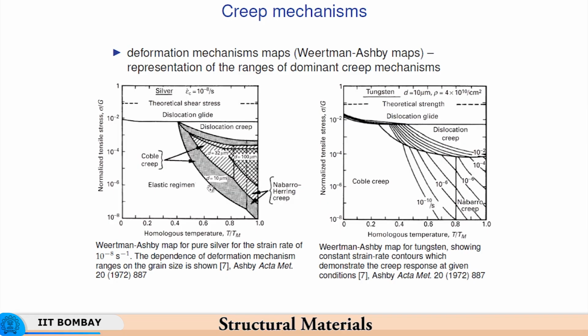Now, here this creep is also grain size dependent. For instance, at grain size equal to 10 microns for a given homologous temperature, you would have creep taking place at a relatively lower normalized stress as compared to 32 microns, which requires a much higher normalized stress for the creep to take place, which means that as the grain size increases, the resistance to creep is increasing. So, that is the point being made here. And then you have at very high temperatures, beyond 80 or 90% homologous temperature, Nabarro-Herring creep. You have Nabarro-Herring creep in this region, and that is a creep which involves diffusion of vacancies through the lattice, right. Okay. So, this is about silver.